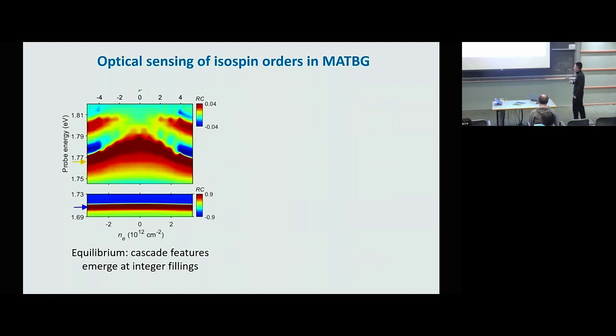And again, it works. Here, again, we are seeing an absorption spectrum of the WSe2 layer, which is in direct contact with the MATBG. And the horizontal axis is the filling. In all these structures, because the Dirac point or the flat band of graphene sits deeply inside the band gap of WSe2, when we dope the system, we're only doping graphene, and WSe2 is always charge neutral. So that's why the 1s exciton just doesn't change.